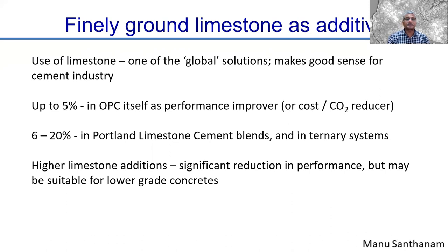Now, one can try and do concretes with limestone content exceeding more than 20% of cement replacement. But obviously, what you're doing here is replacing a reactive material with a non-reactive material. And the fineness of limestone is only going to do so much for improving your concrete properties. After some time, after increasing amounts of limestone replacement, you are obviously going to get some problems of dilution of the cementitious component, and that will result in loss of strength and durability.